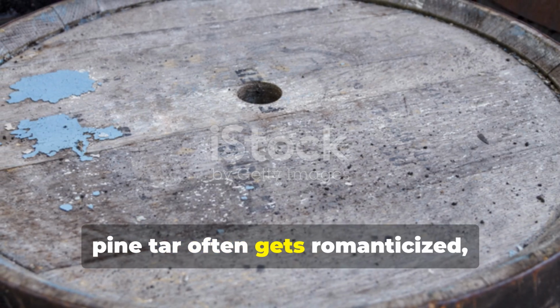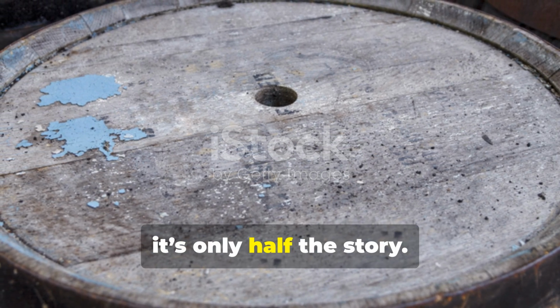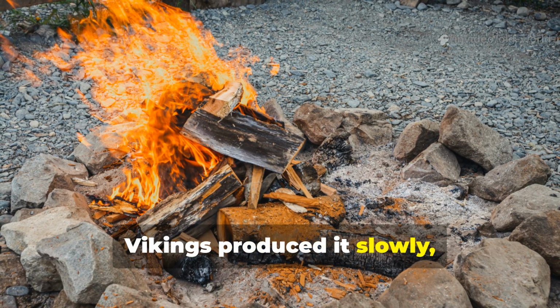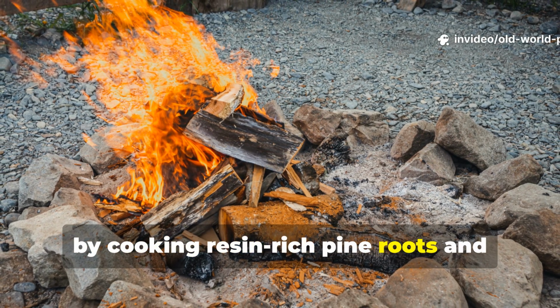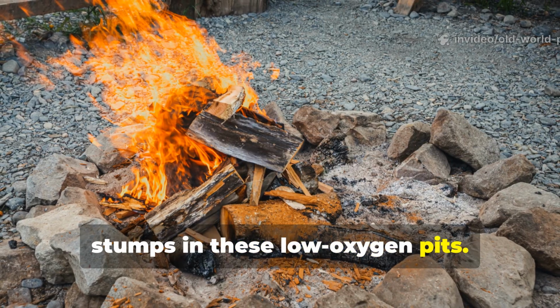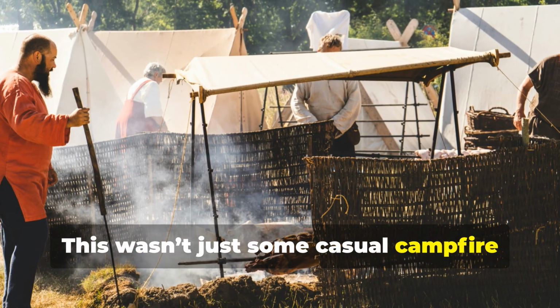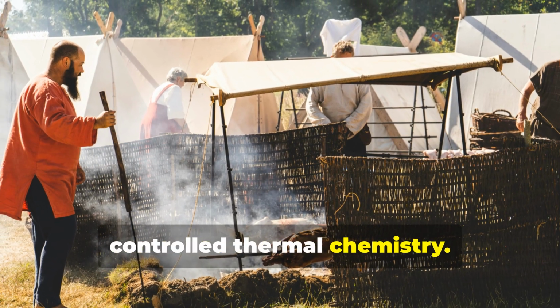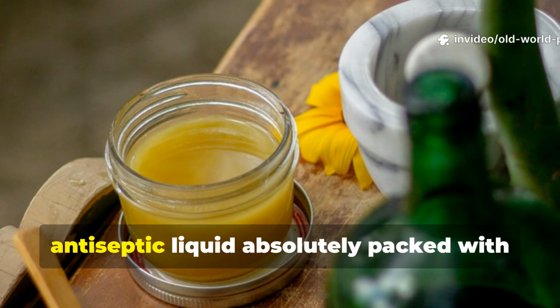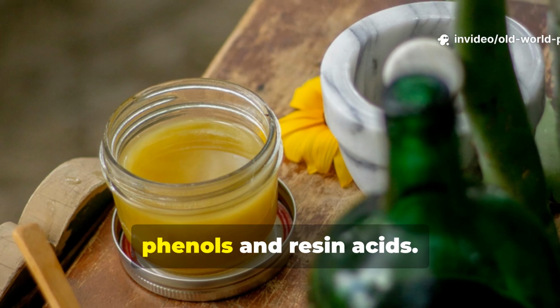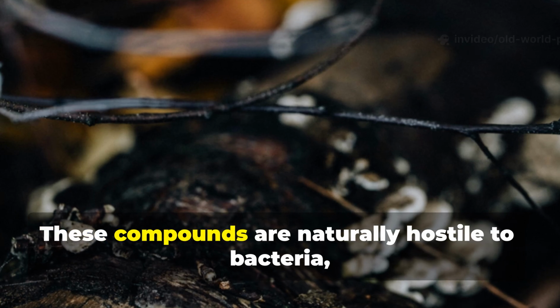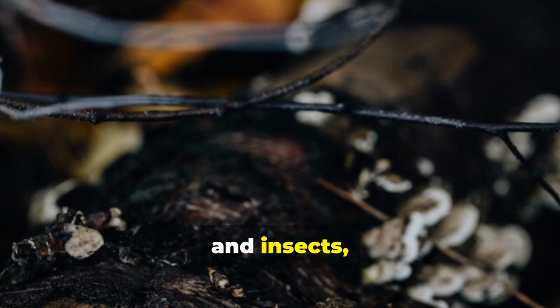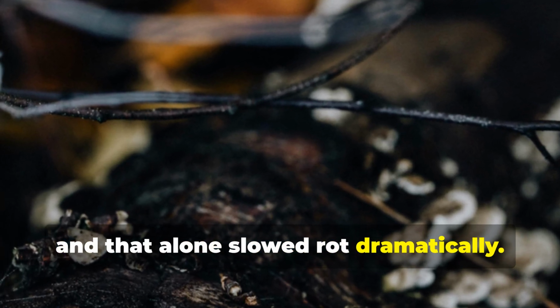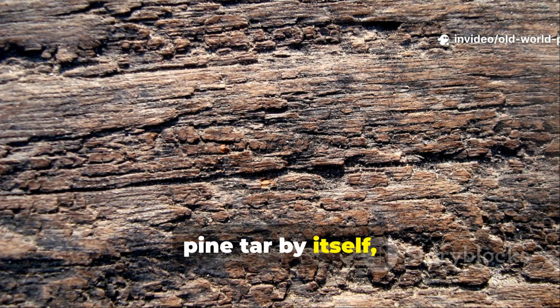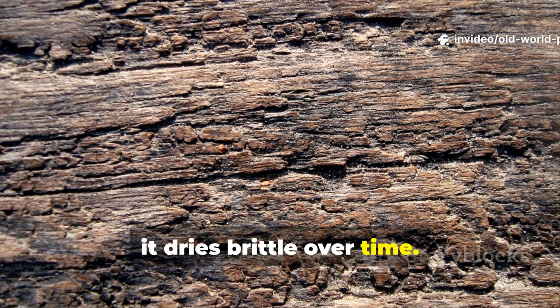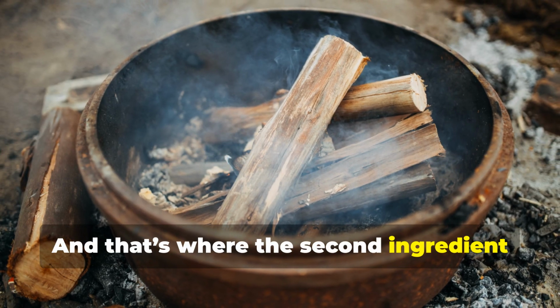So, pine tar often gets romanticized, but honestly, it's only half the story. Vikings produced it slowly, by cooking resin-rich pine roots and stumps in low-oxygen pits. This wasn't just some casual campfire work. It was, in fact, controlled thermal chemistry. The result was a thick, antiseptic liquid absolutely packed with phenols and resin acids. These compounds are naturally hostile to bacteria, fungi and insects, and that alone slowed rot dramatically. But pine tar by itself dries brittle over time. And that's where the second ingredient really mattered.